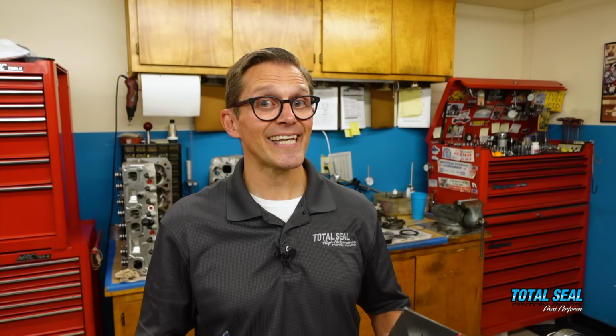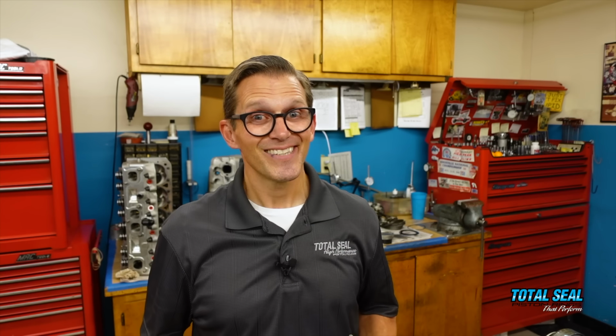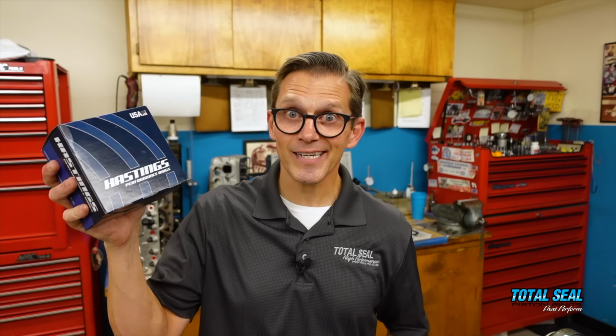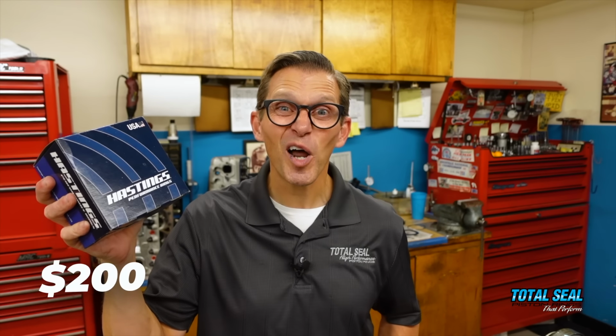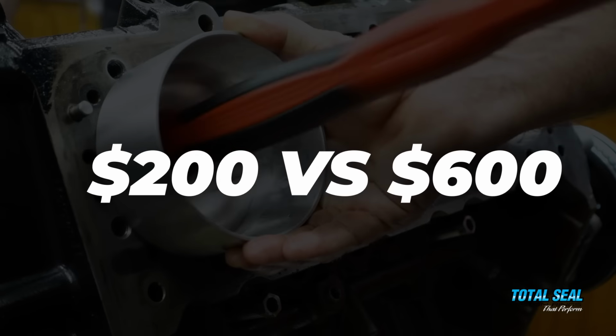Earlier we said this is a $60 versus $600 ring set test. Well, the reality is our $60 5/64th, 3/16th iron ring set wouldn't fit in a modern performance piston. So our ductile moly 16th, 3/16th rings that barely fit in a modern performance piston are actually $200. So it's really a $200 versus $600 ring set test.